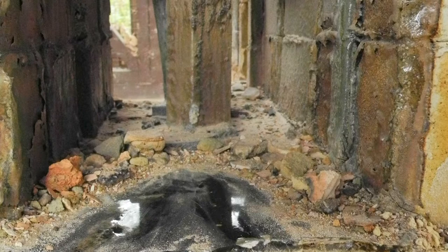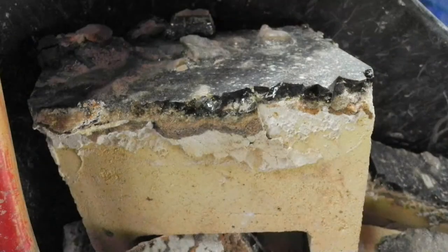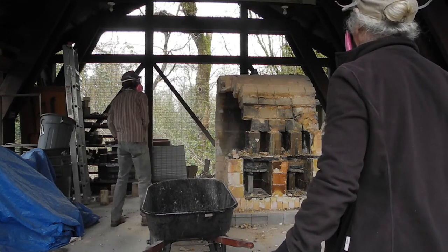As is the case with every wood kiln, its life is limited. Firings take a toll, flues collapse, bag walls buckle, exterior insulation falls off, and interior floors build up layers of melted glass created by liquefied wood ash. A new kiln was needed to replace the beloved Ombu, which was fired for the last time in March 2014 and demolished soon afterward.